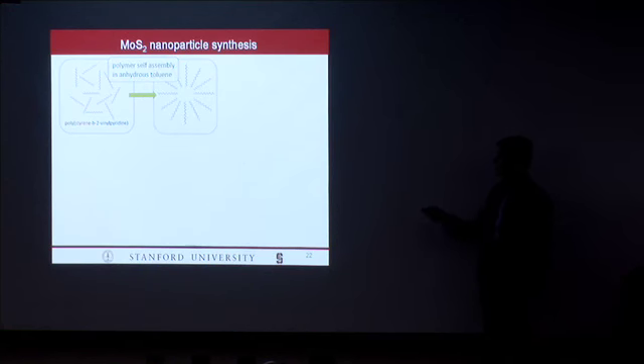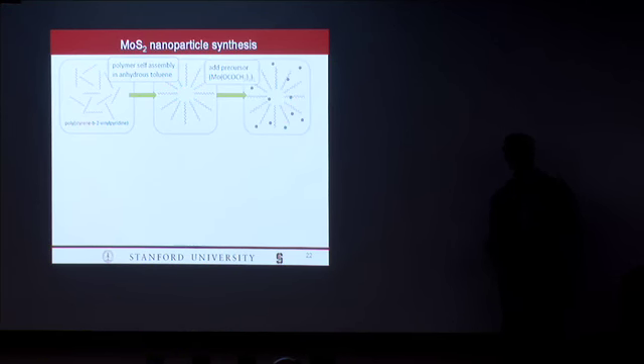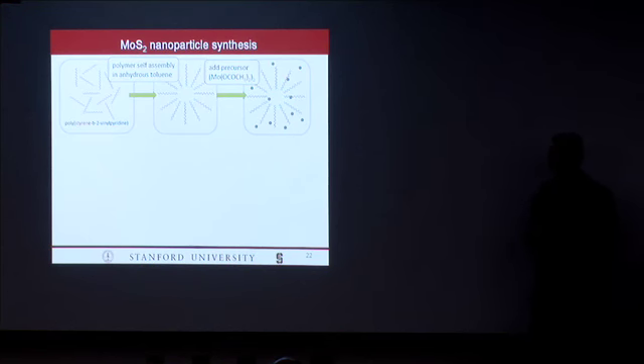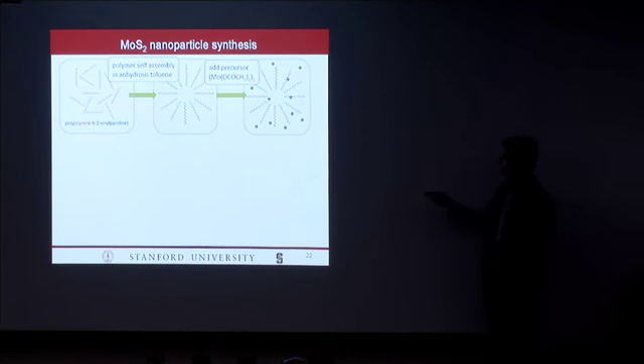So how do we go about synthesizing MoS2 nanoparticles? We start off by taking a block copolymer which has two different sides. It has a polystyrene tail and a vinyl pyridine head. We dissolve this inside a hydrophobic solvent, and you get an assembly such that the hydrophobic tails are extending outwards and the hydrophilic core is shielded on the inside. Then we add a molyacetate precursor. This prefers to be in the hydrophilic part of the micelle, so the moly precursor migrates into the middle. We end up forming these micelles that are loaded with metal right there at the core.